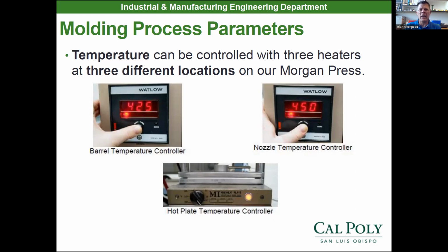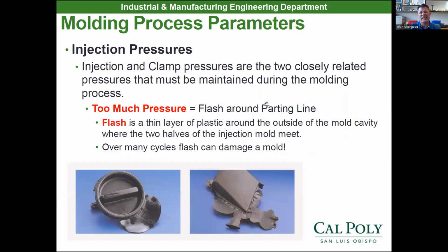So we're going to use that hot plate controller to warm up the mold to about 200 degrees Fahrenheit before we injection mold there. And that keeps our mold at a constant 200-degree temperature throughout the day, throughout molding. So technically, we're keeping it cooler than the melting temperature, but we're warming up our mold in this case. Bigger machines have cooling jackets and they keep it at a constant, steady temperature as well.